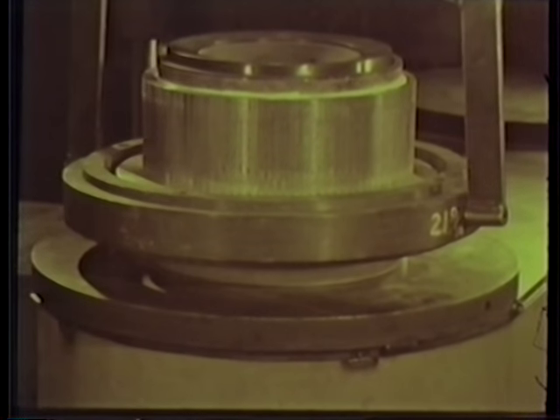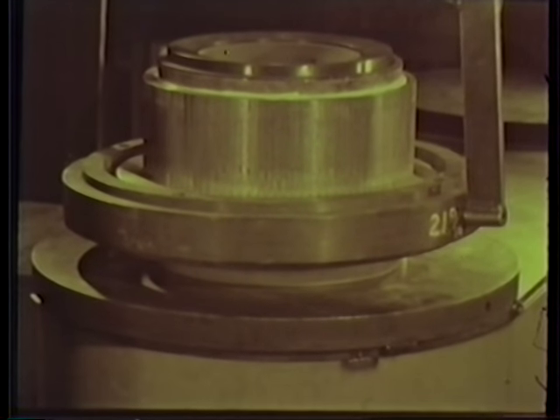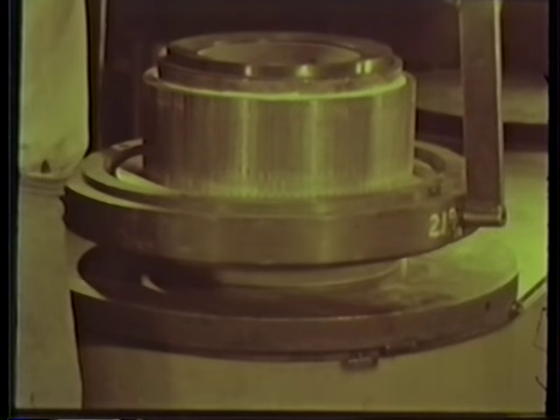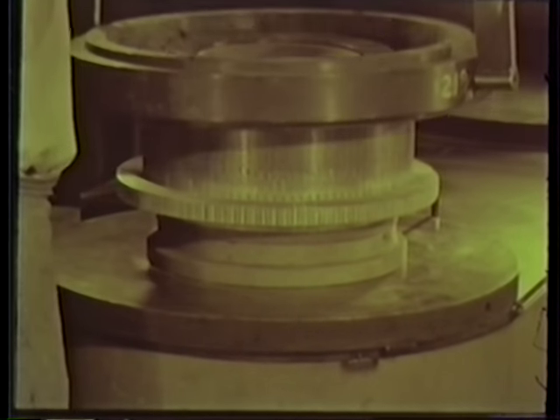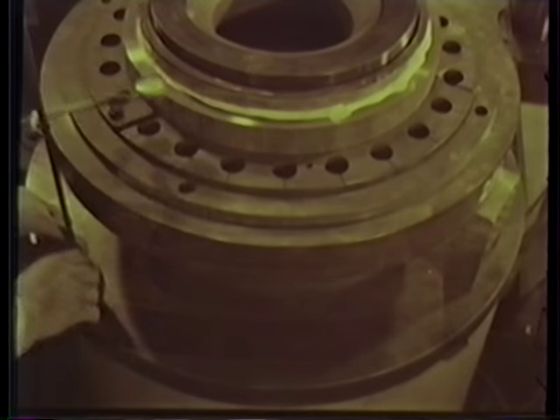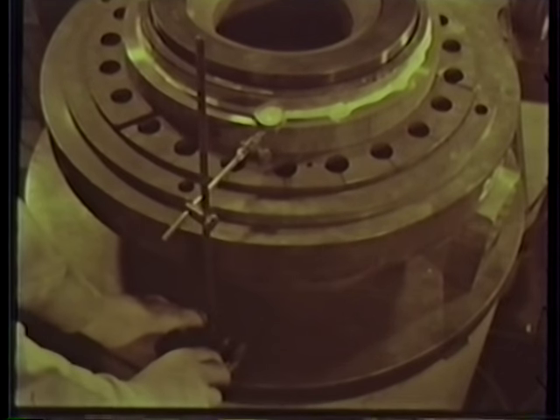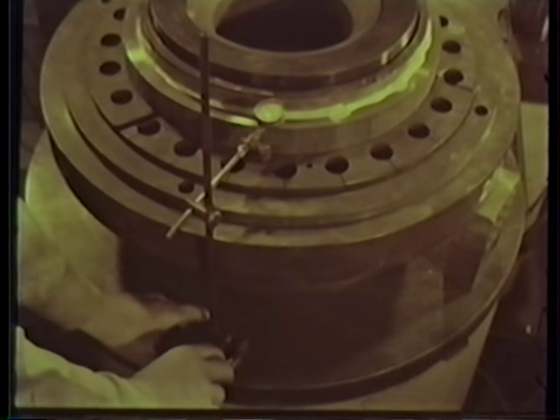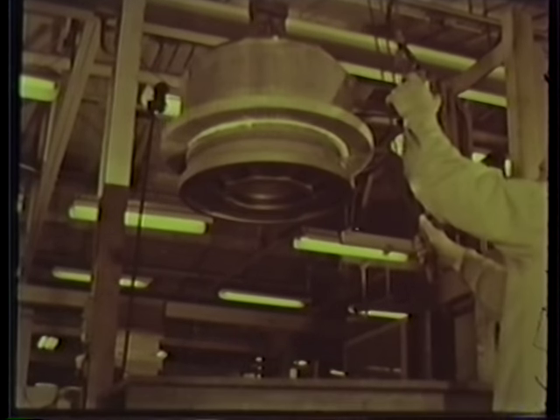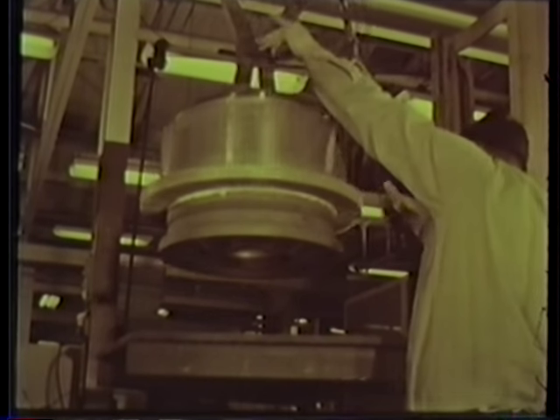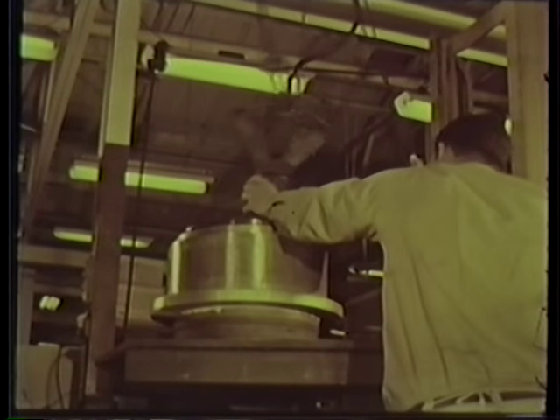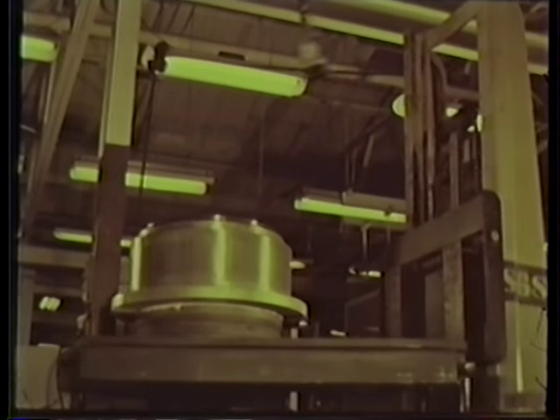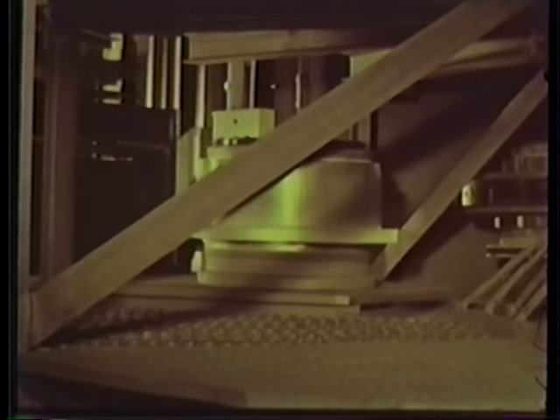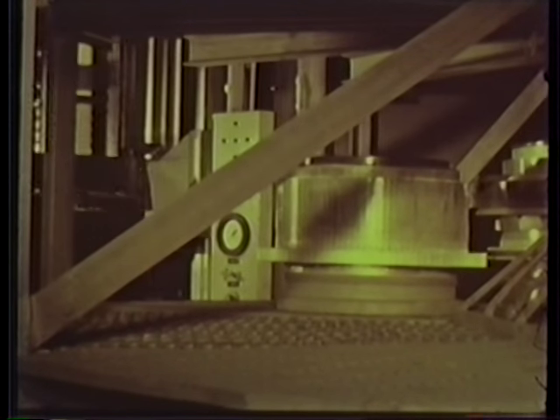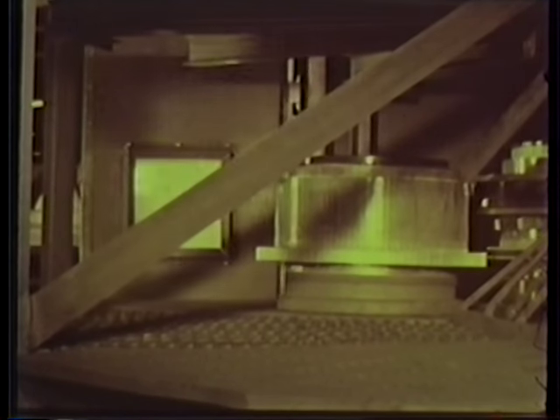No longer needed to hold the copper and mica segments in alignment, the building rings are removed to leave the commutator sustained now for the first time by its own internal pressures. Gauge accuracy must be maintained. No segment is allowed to shift during baking and pressing. With the retaining pressures now on the end rings, the unit returns to the oven, where further heat application will cure the mica parts in their final position. This cycle of baking and pressing may be repeated several times until TEMCO is certain that the commutator is dimensionally stable.